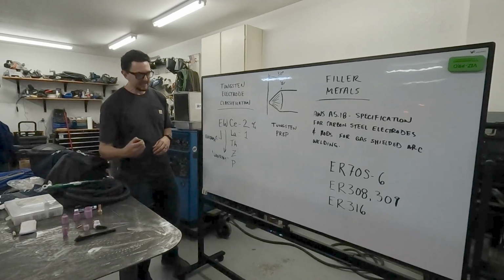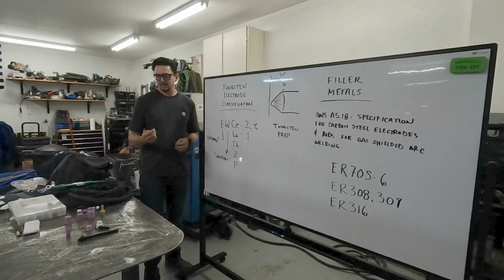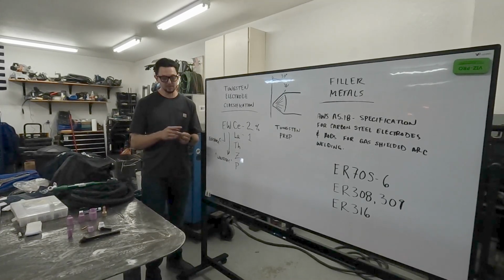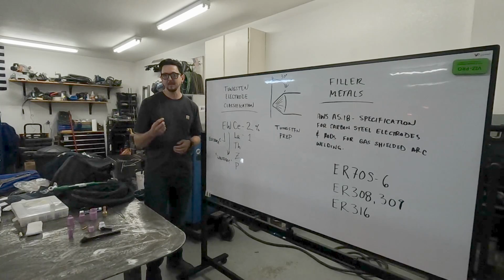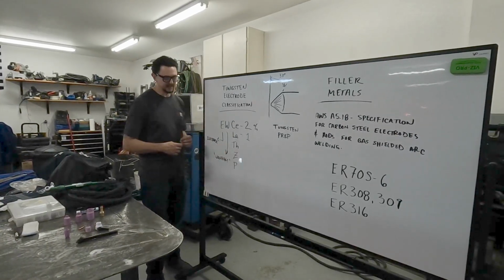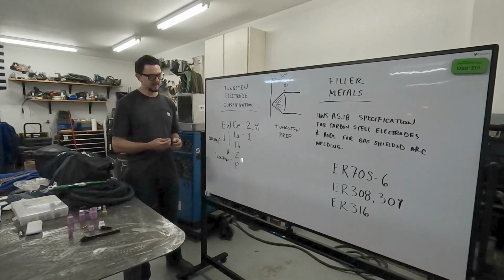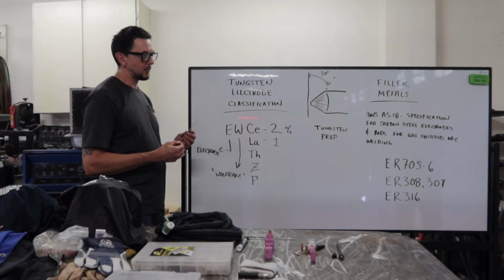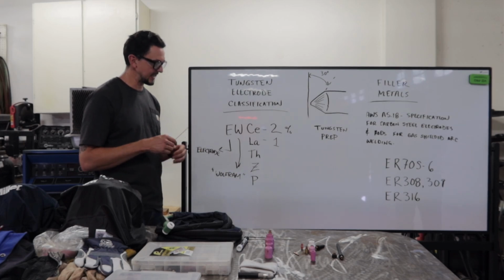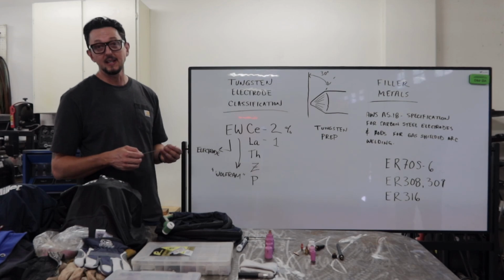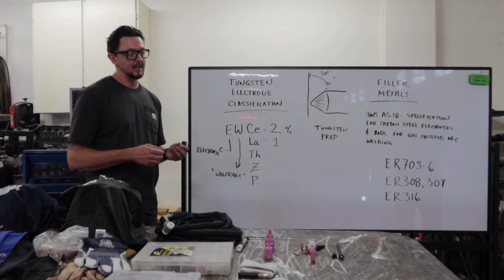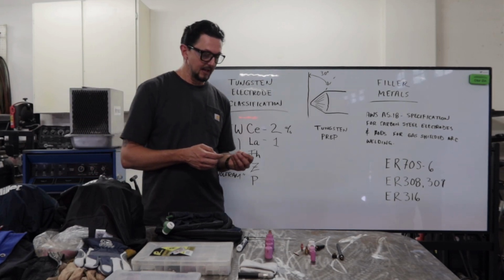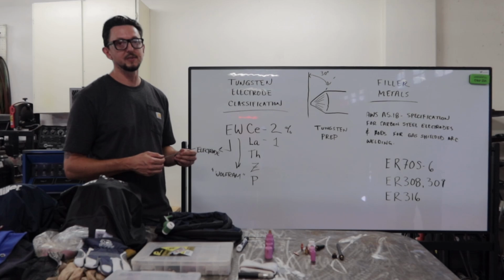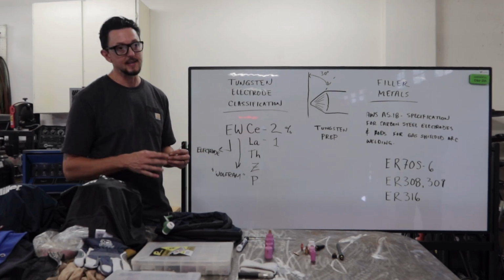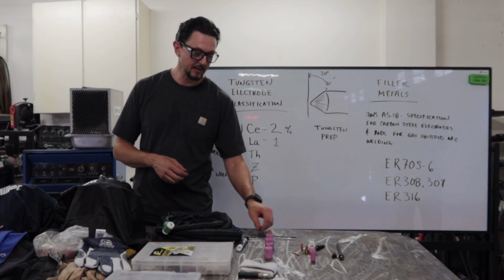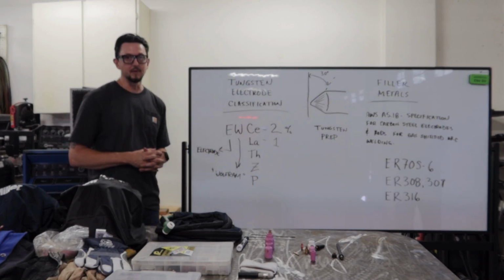The one other thing that I wanted to say about the types of tungsten electrodes and the colors is that the red band, which is red for a reason, to give you a little bit of caution, is a thoriated tungsten. The oxide type that's thoriated is actually radioactive. So when grinding these, you need to take care not to breathe in any of the grinding dust because it can be a carcinogen. For that reason, we don't use these in the schools anymore, and typically industry shies away from them now because they are radioactive and the grinding dust can be harmful.